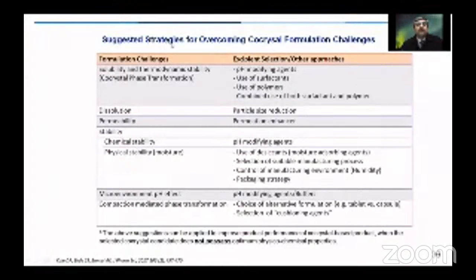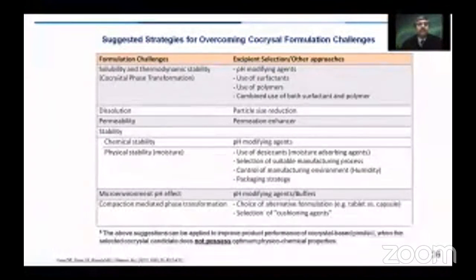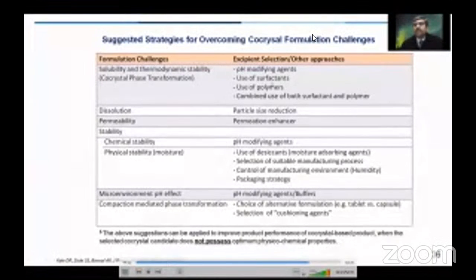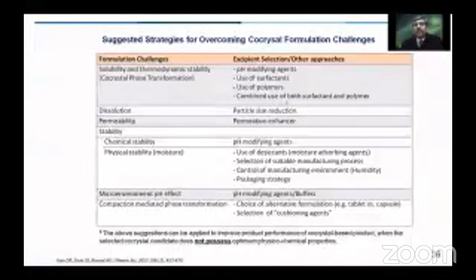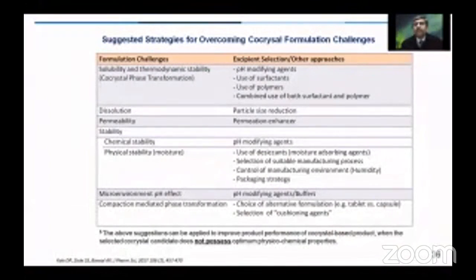This is a general discussion on some of the suggested formulation strategies for overcoming the challenges that are posed by co-crystal during the formulation development. Some of the co-crystals will show very fast transformation to the API, which will be reflected as a spring effect. And in those cases, we will have to delay this conversion of the co-crystal to the API if we have to harness the solubility benefit from that particular co-crystal. This can be done either by using pH modifying agents or using surfactants, using polymers, or a combined approach involving surfactant and polymer. These are targeted at delaying the supersaturation from the co-crystals so that the benefits that we want to obtain from the solubility of the co-crystals can be obtained.